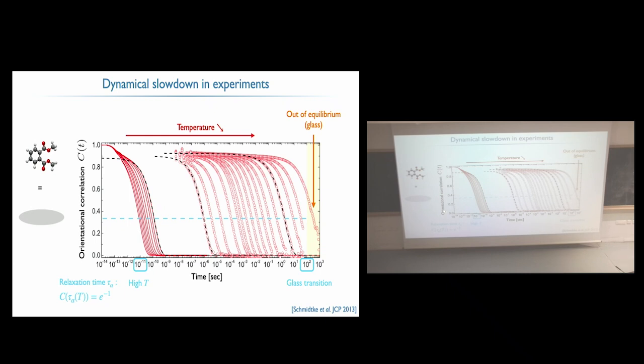So what you can compute indirectly is the correlation of the orientation. So let's imagine at time 0, which is in log scale, so to minus infinity, you have the molecule placed like that. You're going to probe how it's reoriented, and this is supposed to tell you whether the liquid has flown in this region or not. So what you see here, it starts from 1, and at high temperature, which are on the left, it decreases, it decorrelates to 0. And this means that at this time, 10 to the minus 11, after 10 to the minus 11, the structure has completely rearranged. So it's a fast-flowing liquid. But as you decrease the temperature, you see that this curve extends to the right.